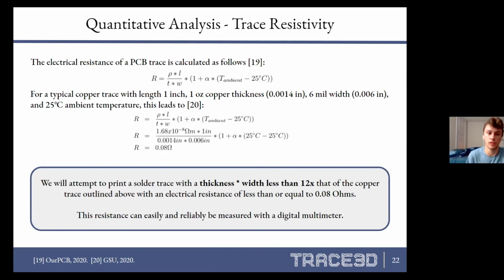So moving on, we looked at the trace resistivity of a typical copper trace using some standard values of a length of 1 inch, 1 ounce copper thickness corresponding to 1.4 thou of an inch, and 6 thou inches width of the trace. With a 25 degrees Celsius ambient temperature, this led us to a resistance of 0.08 ohms.